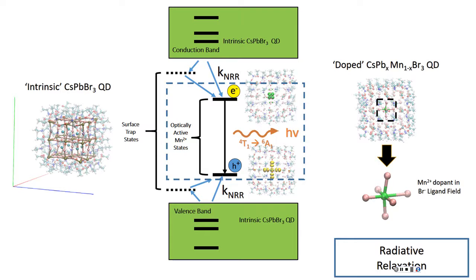Well, this got edited a little bit. But anyway, now we're looking at radiative relaxations that can happen in these systems. Non-radiatively, the holes and the electrons relax to the band edges of the dopant, illustrated here. But you can also have PL that comes intrinsically from the perovskite, because in experiment they do see dual emission from the same samples.